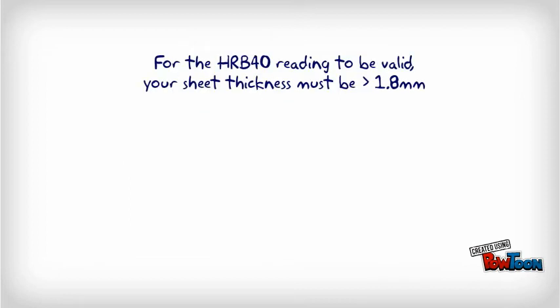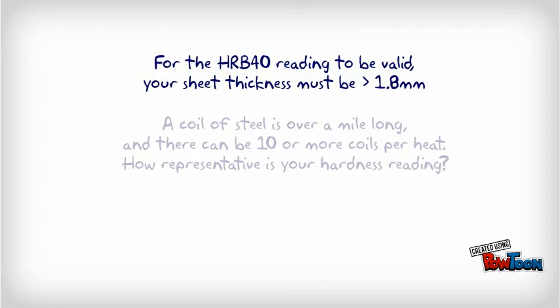Some of the other issues related to hardness testing include: for the Rockwell B40 reading to be valid, your sheet thickness must be 1.8 millimeters or thicker according to ASTM specifications for hardness testing.